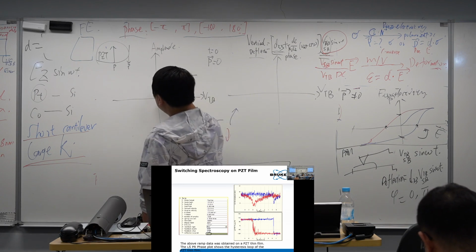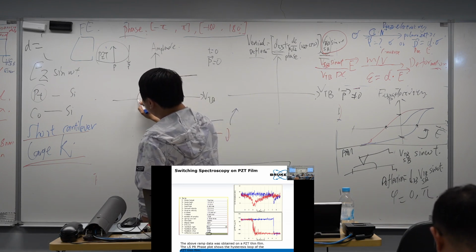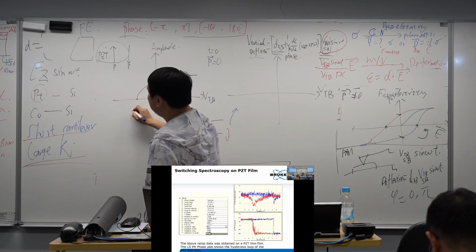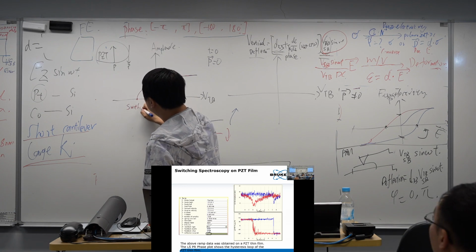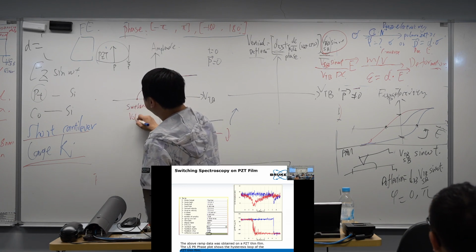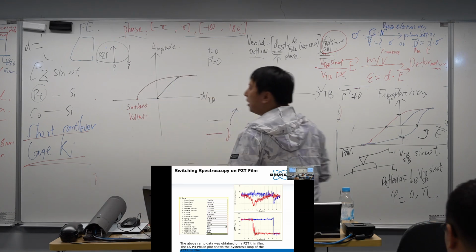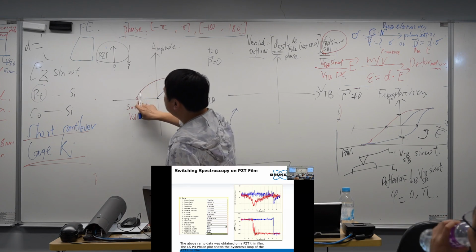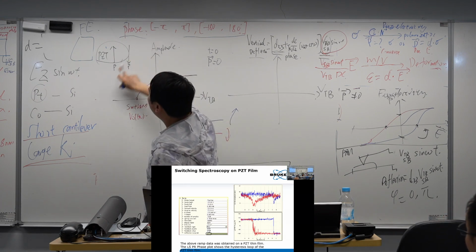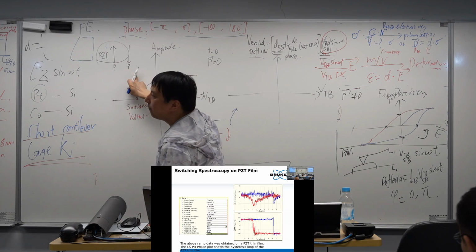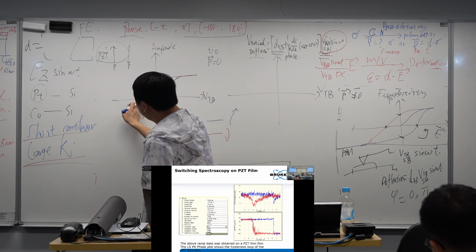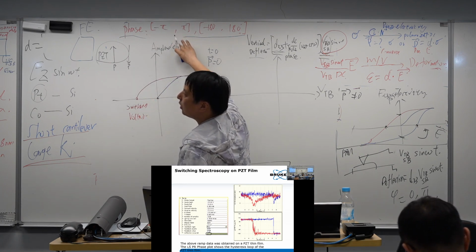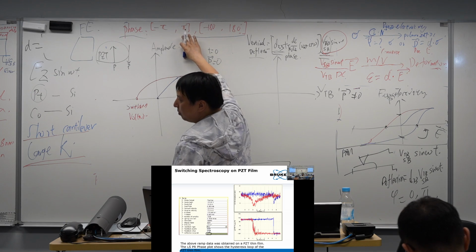And then I go down to reach the coercivity, and this coercivity we call the switching voltage. After this point, I start to change the direction from facing up to facing down. So my polarization should reduce, but I am detecting the amplitude, which should never go below 0.